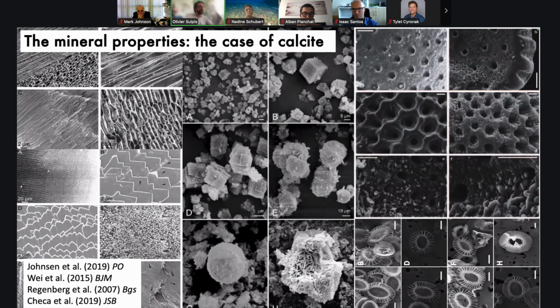Now there is reality. It's not as simple as this, because in the real ocean, if you look at the surface of calcium carbonate minerals, here I don't even know what I'm showing you here. It's just to tell you that if you zoom in, if you look at those crystals with an SEM, they have all kinds of shapes. For example, if you look at coccoliths, it's really not just a nice cube, like what we saw in the slide before. Actually, in 1 gram of coccolith ooze, you have as much surface area as in the room I'm sitting in right now. So there's so much surface area, so many little pores everywhere. Then it makes the prediction of those dissolution reactions much more complicated.